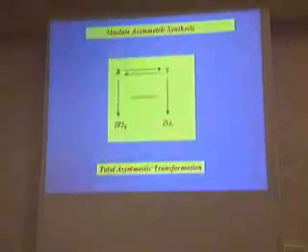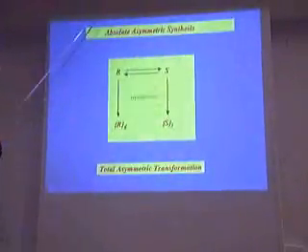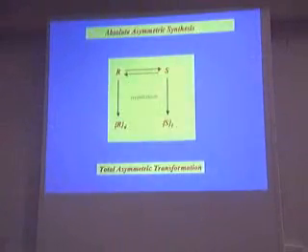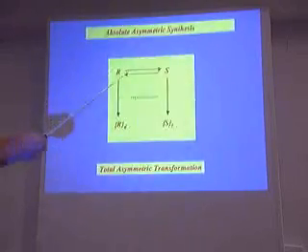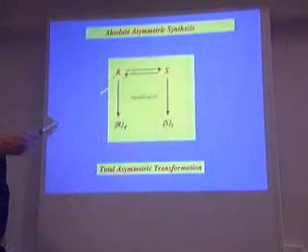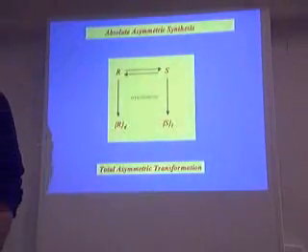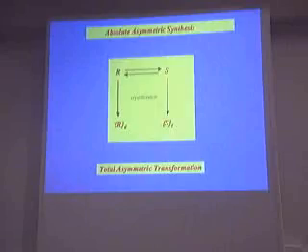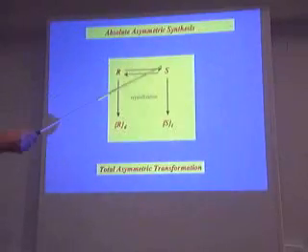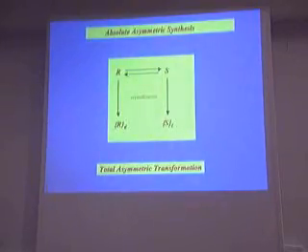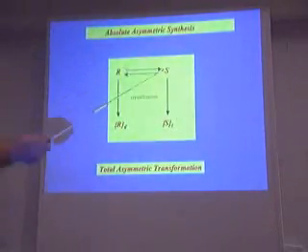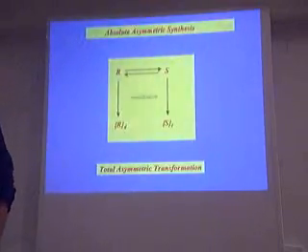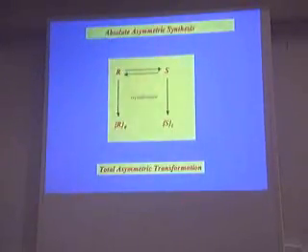So what we saw is that in principle in crystallization you can materialize, experimentally, the Pasteur model. If you have a fast racemizing system and you crystallize it, this is what Havinga performed a long time ago. This was the first experiment, followed by Powell and others, what Kurt Mislow would call a total asymmetric transformation. People today are using new terms, but the old term is total asymmetric transformation. You can convert a racemic system into a crystal of single enantiomers if you perform the crystallization under controlled conditions.